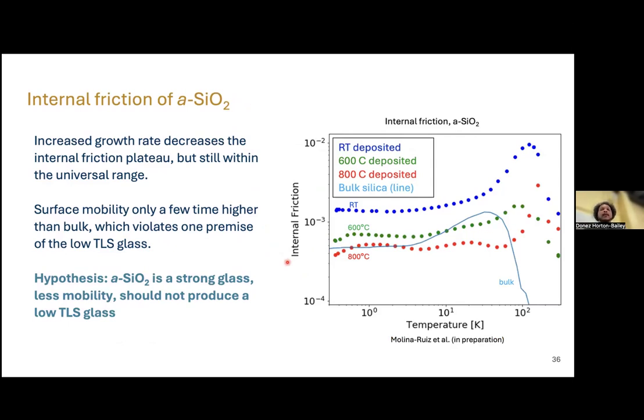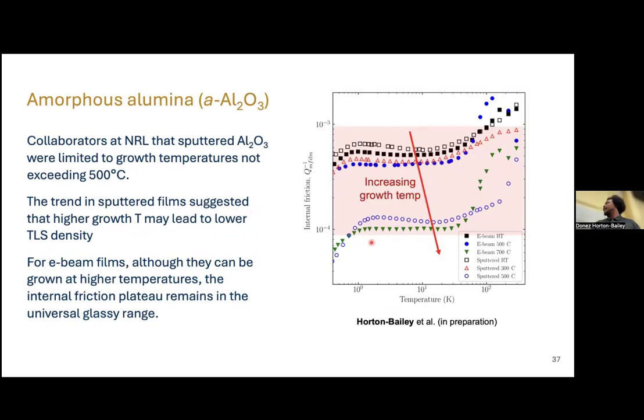Similar idea with looking at the internal friction of silica. We see that increasing the substrate temperature during growth actually decreases the plateau level. So we are seeing a decrease in the TLS density, but we're not seeing anything that's ultra low or anything that's significant for the applications that I mentioned.